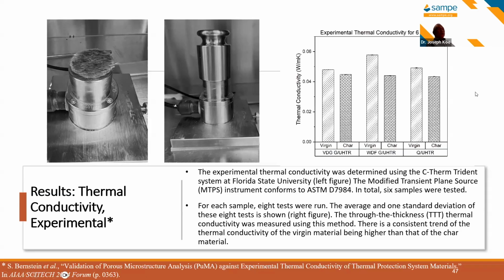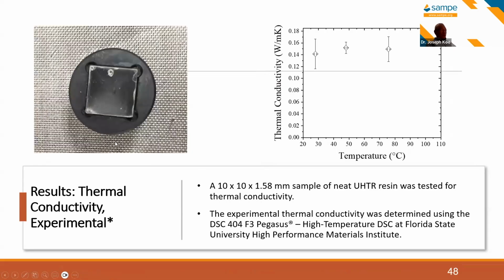We sent the materials to Florida State, and they have an excellent, high performance laboratory there. So we were able to measure the thermophysical properties of these materials that we are developing, and we were able to measure through the thickness. And in order to calculate some of these, we have to measure the thermal properties of the virgin and also of the fibers. The thermal conductivity measurement was done at Florida State, and for the fibers we were using the technical data sheet from the fiber manufacturer.